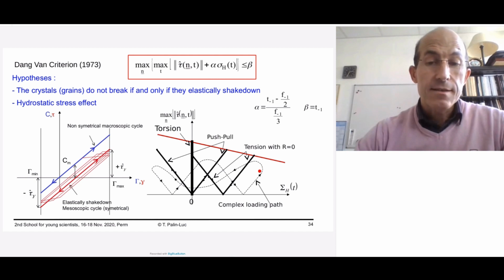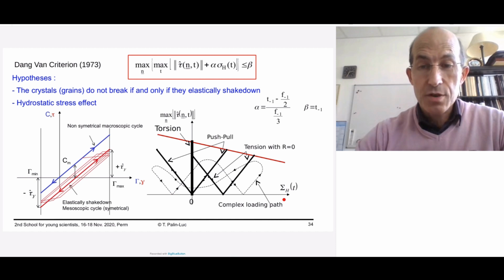And in this case, like for Crossland, the diagram plots versus time the evolution of the amplitude or the norm of the shear stress vector in a material plane versus the evolution versus time of the hydrostatic stress. And like for Crossland, there is a threshold depending on the material properties, the fatigue number of cycles considered, like 10 to the 7, for instance, and the probability of failure.